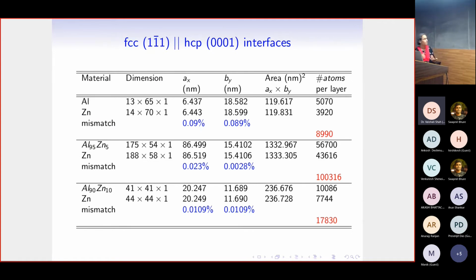So now we have a surface that we can generate. We have an interface that we can generate. We know what are the dimensions of these surfaces we need to work with, and what is the area of the surface we would be working with. So this comes in some nanometers. And what is the number of atoms per layer we would have to work with. So in this case, it comes out close to 9,000 for the aluminum zinc interface. Whereas if we look at the aluminum 95 zinc 5, it comes out very close to 100,000 atoms.